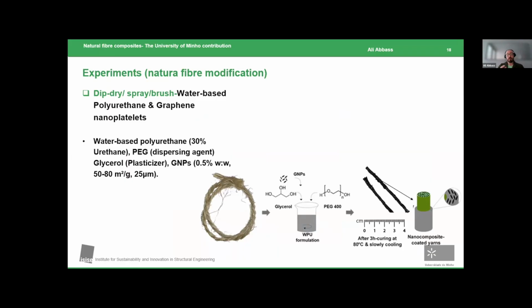So this dip dry coating would comprise a polymeric formulation of polyurethane. We would add glycerol as a plasticizer to control the flexibility of the coating itself. Then we would add a dispersing agent, which is polyethylene glycol, to homogenize the distribution of graphene within the polymeric matrix. So we're talking about a nanocomposite material. It has the same concept, nano-reinforcement and a matrix. Then we would prepare this through homogenization in ultrasound. We apply high shear of 15,000 rounds per minute, and then we apply it to the fibers and we heat treat it, and we obtain, as you can see, these black nanocomposite coated natural fibers.